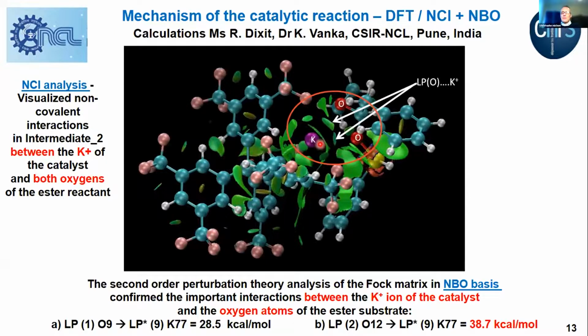The interaction between the potassium cation and the oxygen of the esters was also illustrated and confirmed by NCI analysis and also by NBO treatment. Favorable energies of around 38.7 kilocalories per mole were obtained for these interactions.